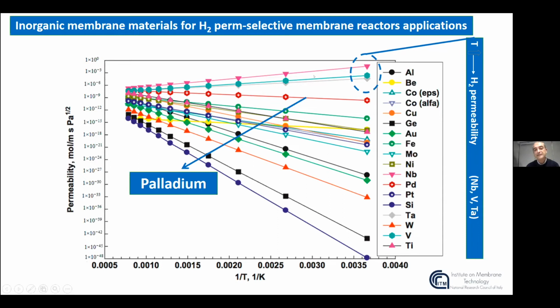Unfortunately, for these metals, hydrogen embrittlement is the worst effect that can happen, and this occurs because when we expose these metals to a long-time operation hydrogen permeation test, the membrane can become brittle and then it fails. Therefore, palladium today is the dominant membrane material for separating and purifying hydrogen. Unfortunately, in this case, the permeability of hydrogen for palladium membranes increases with increasing temperature, but it is the highest at the related temperature with respect to other metals.